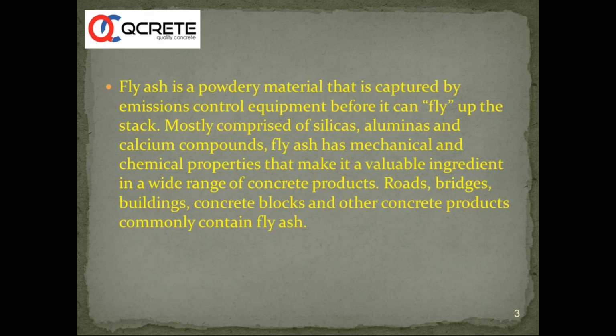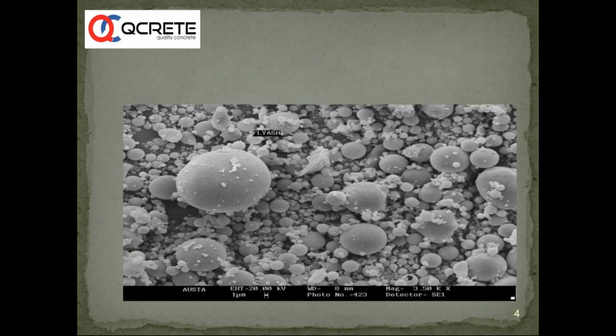Now things have changed a lot because a lot of uses of Flyash have been found. Now, the beauty of Flyash, if we look at it under an electron microscope, is that the particles are spherical in shape, and this gives very good workability in concrete and a ball bearing effect. The spherical shaped particles move over each other and give lubricity to the concrete mix, and pumpability will be increased. So the sphericity of these particles makes a big difference when we are using fly ash as an SCM.